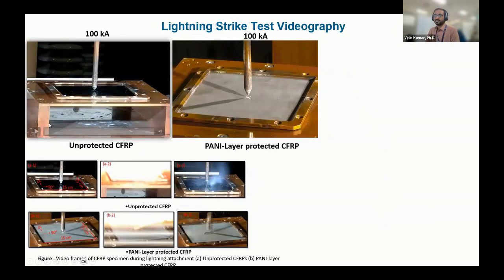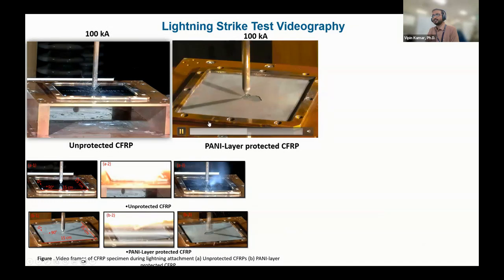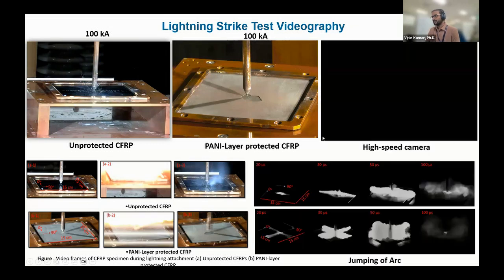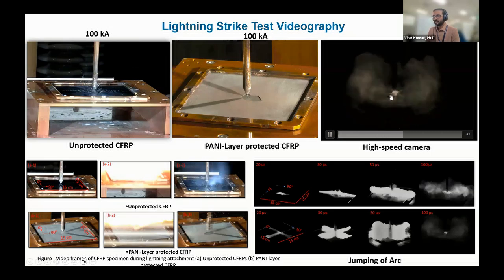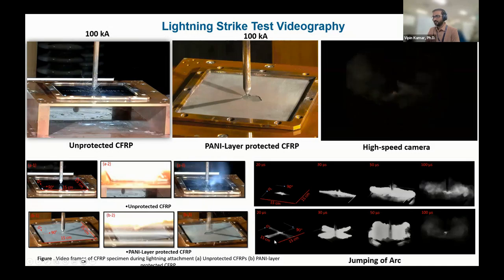So now what will happen, as I said, if there's no coating on it, you see a damage. Now this is a 0.25 millimeter thick coating on the CFRP composite laminate. So you see the composite laminate is still safe, but the coating did see a damage. The reason is very clear: the coating acts as a Faraday cage. It keeps the current on the outside of the laminate and dissipates it to the ground. You can see it took its closest line, the shortest distance to reach the ground. That's why your composite laminate is safe.